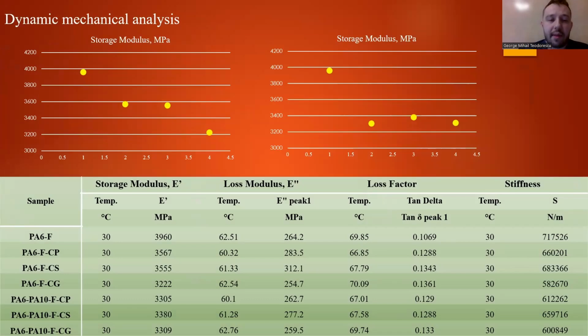So firstly, looking at the dynamic mechanical analysis, the results show that for the PA6 series, a decrease compared to PA6F, which is let's say a neat polyamide 6 with 30% glass fiber, no added ash or bio-based polyamide 1010. We saw a decrease in storage modulus and stiffness by 5 to 10% for the composites treated with the polyester and the metal salt, and 18 to 19% for the composite treated with the silane. An increase in the loss modulus and loss factor is observed for the metal salt treatment and the polyester treatment, indicating an improvement in viscous properties due to strong polymer ash matrix adhesion.